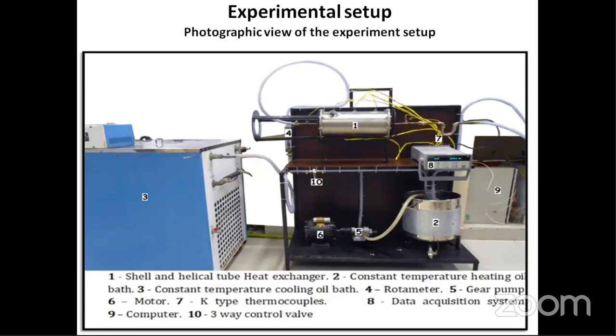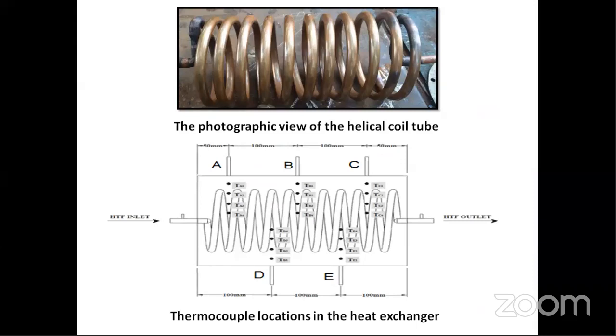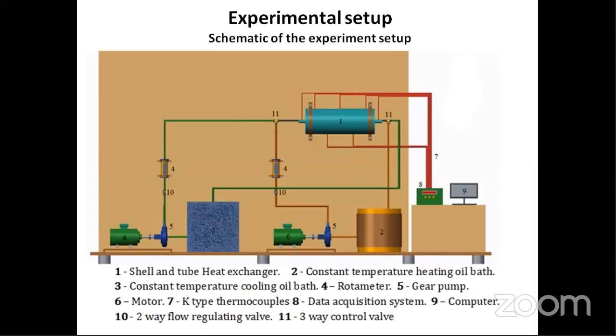It consists of a heat exchanger, high temperature path, low temperature path, circulation pump, K-type thermocouples, data acquisition unit, and necessary pumping systems. The heat storage container consists of a tube surrounded by heat storage material. It's a photographic view of the helical coil tube. Here we are using 20 K-type thermocouples with a measuring range of 0 to 270 degrees Celsius, located in the axial direction. Two thermocouples were placed at the inlet and outlet of the tube. As a schematic of the experimental setup used for charging and discharging experiments, 88.5 kilograms of heat storage material was loaded in the heat storage system.